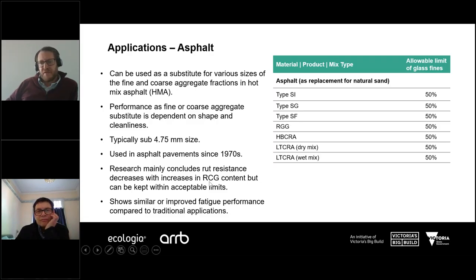But typically in asphalt, we could be allowing a 50% replacement of the fine aggregates with glass fines, and that's typically for asphalt bases. We might have a few more concerns if we were to consider a wearing course, where we could be concerned that glass particles could pluck out of the surface, and therefore to overcome that we would consider a lower upper limit on the glass content, which could be around 5%.